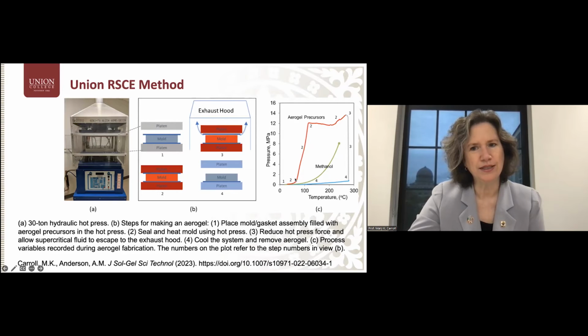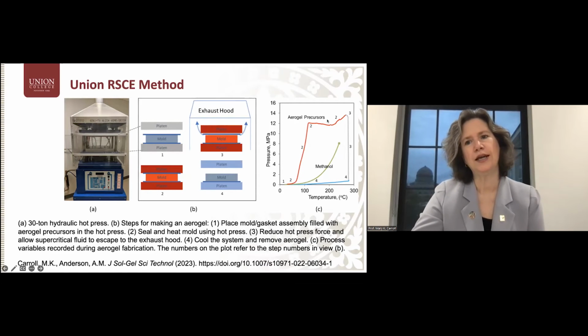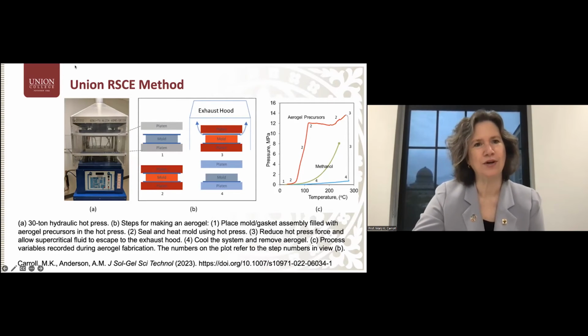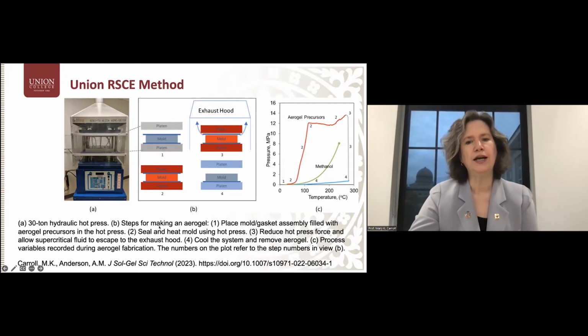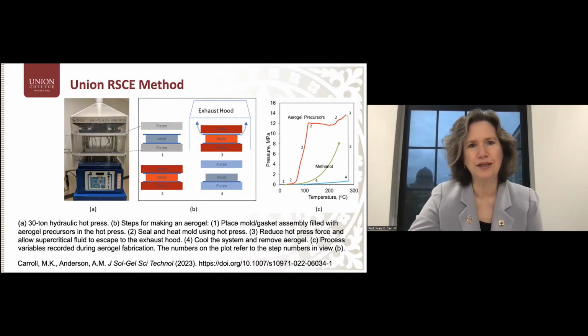We start increasing the temperature, and as we increase the temperature, the pressure increases, and you can see that we get above the critical point. We release. Now we have a very hot aerogel, and we cool it down, and then we have the aerogel. So we have recently published, I think it's available online, not yet in the print version, a retrospective article on the 20 years of work that we have done with this method.